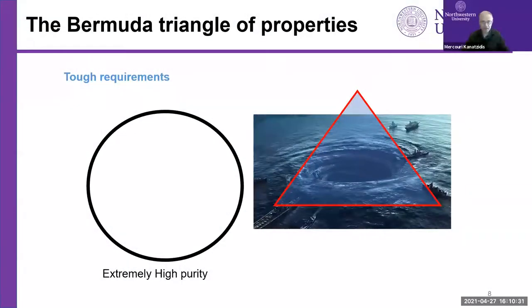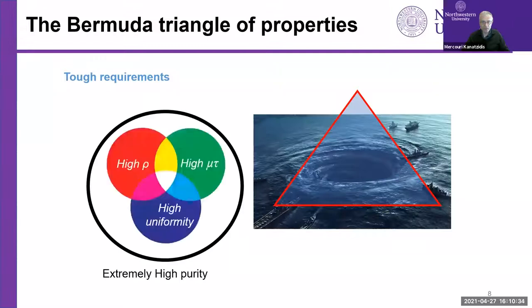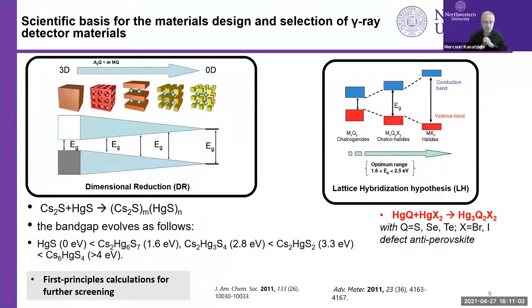for gamma ray detection. So in this field, there's a big challenge for the properties. What we call the Bermuda Triangle: we need three properties to be all together in the same material. High resistivity, very high mobility lifetime product, and good uniformity across the crystal. In other words, a low number of defects. If one of these three is missing, you are in trouble and you're going down. We came up with chemical concepts that actually allow us to find many, many promising materials.